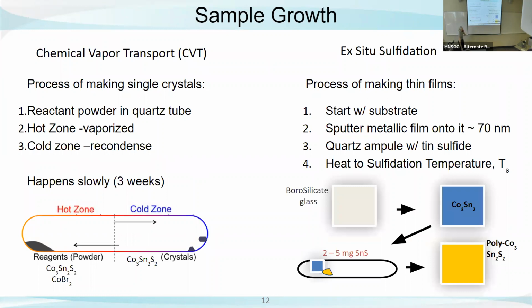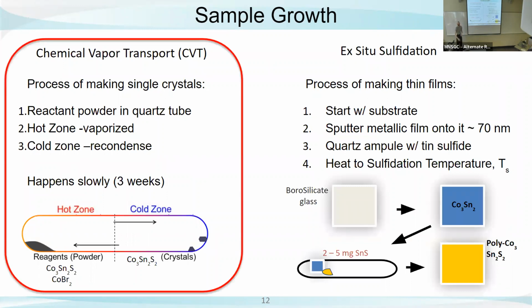So I'm going to shift to my single crystals. We use chemical vapor transport to make our single crystals. We load a reactant powder with a transport agent on one side of a quartz tube, and then we seal it. And we put it in a gradient furnace with a hot zone and a cold zone. We vaporize our reactant powders, and then they would travel and cool and recondense as single crystals in the other side. But this process is like super long, takes about 3 weeks. So it's not generally an easy process to go with.